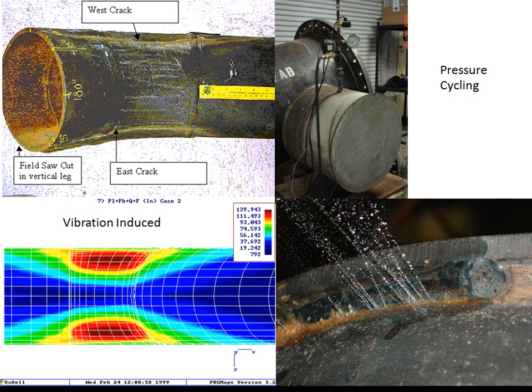The rightmost figures show a crack and leak that occurred due to pressure cycling of a vessel with a welded flat head. This test was run by Chris Hennett and used to help verify the fatigue method used in Part 5 of Section 8, Division 2.